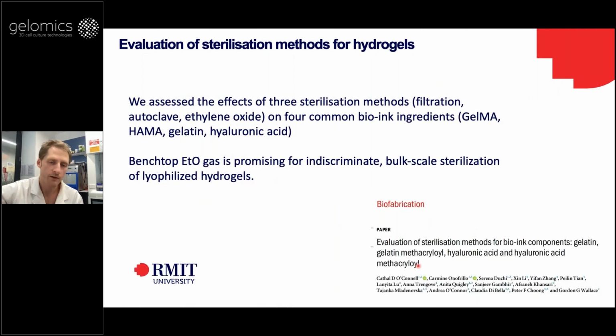The take-home message is that of those that we tested, ethylene oxide gas, which is commonly used in the medical device industry, was very promising for bulk sterilization of these hydrogels. The gels, or the lyophilized powders, that we tested were GelMA, HAMA, HA, and gelatin itself. So we tested all of those under all of these conditions.